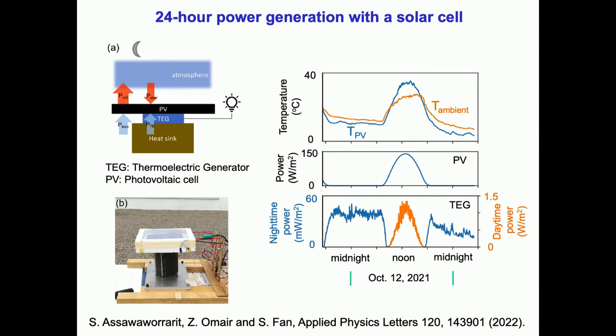And as I mentioned, almost any material you can make into a radiative cooler. And so one of these material systems that you can do is, in fact, a solar cell. The encapsulated solar cell has a silica layer on top, which is a very strong radiative cooler. So at night, it will actually have a temperature far below ambient. And based on this effect, we have recently done an experiment where, again, we put a thermoelectric generator on the backside of the photovoltaic, to show that you could actually get electricity out at night from a solar panel using this kind of technique. The experimentally observed power density that we see here at night in this particular experiment is about 50 milliwatts per meter squared, which is a very modest amount of electricity. It's enough to drive a light emitting diode, but it's not that much power.